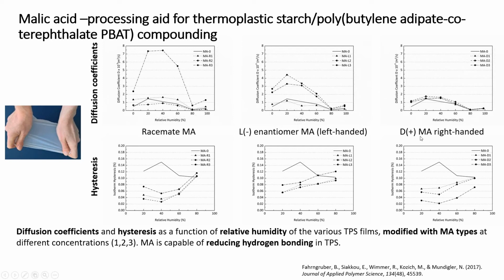malic acid additive. I would say this was not a very applied thing. It was more a curiosity thing, because this is super expensive as an additive. But even so, we wanted to know if it has an effect on the film properties of the resulting thermoplastic starch. And we also looked at the sorption behavior, and you see here, just looking at the graphs and the lines, that they are significantly different. And so that was the first thing we realized, a function of relative humidity of those films.